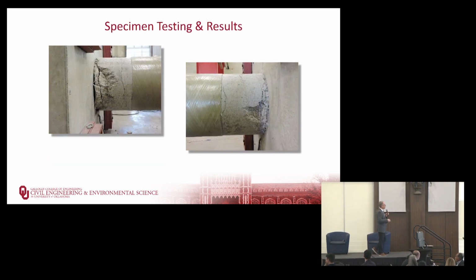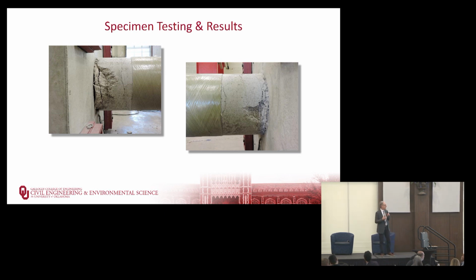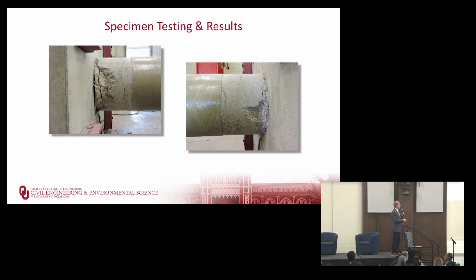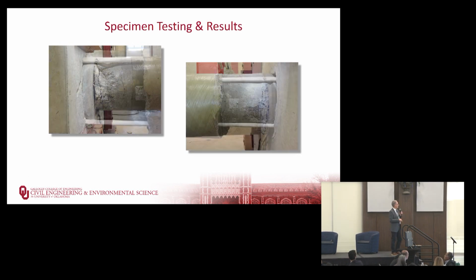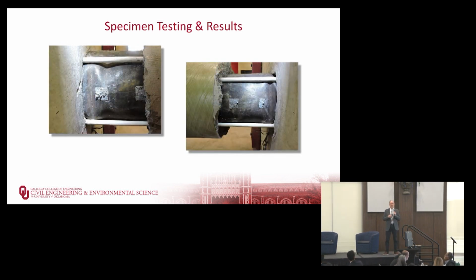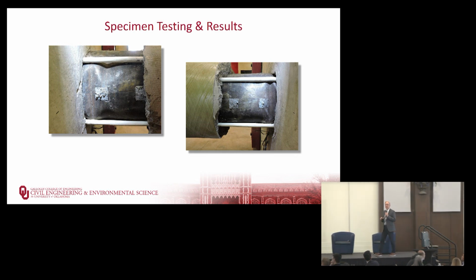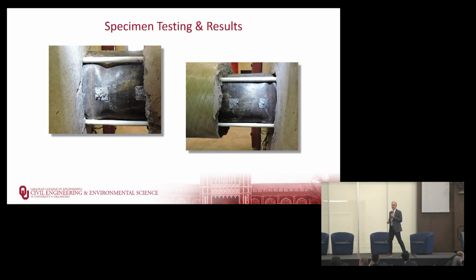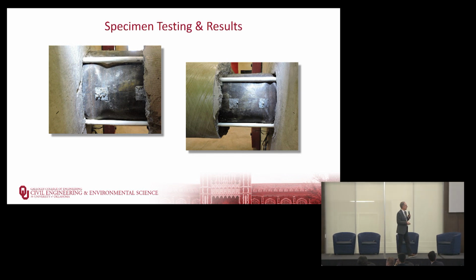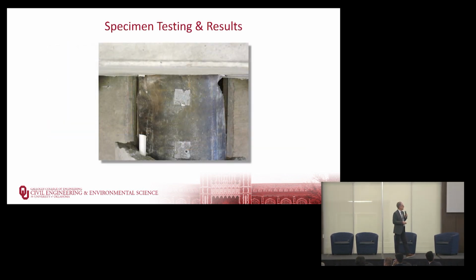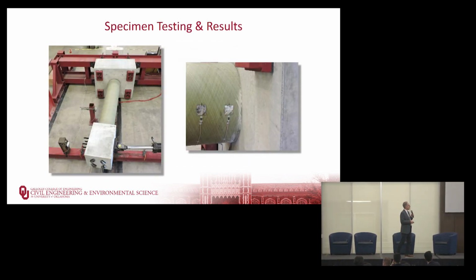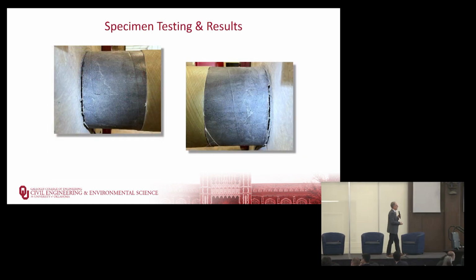And then we strip off the FRP, take the load off. We start looking at the concrete that started to crush in compression, started to pulverize. Typical for even a reinforced concrete column, the core was still keeping fairly strong. Again, no bond to the footing. And then we look at the steel tube. You can see how the steel tube is buckled. Actually, with the self-consolidating concrete, it actually fractured. So it was a low cycle fatigue where we fractured the steel tube. And again, looking down.